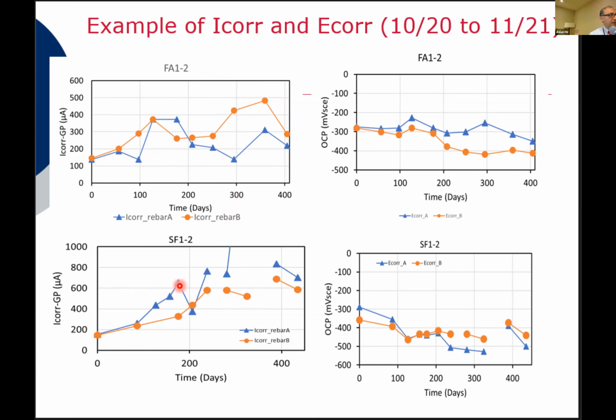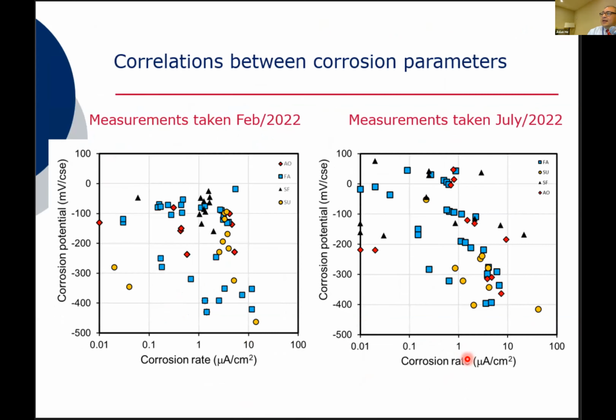In these particular specimens, we actually applied electromigration to add chlorides into the concrete. So in this case, you can see that the observed current ranged anywhere from 200, and in some cases exceeded 1,000 microamps. And the corresponding potential at later times was more negative than 500 versus calomel, which means that it's close to minus 600 versus copper sulfate.